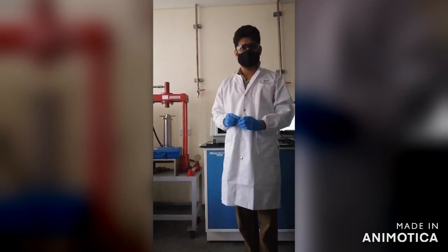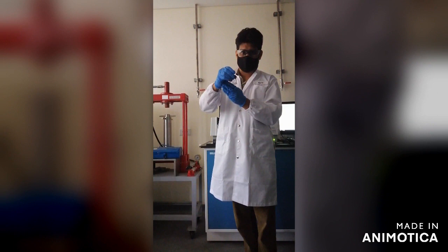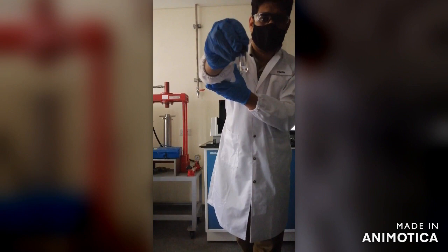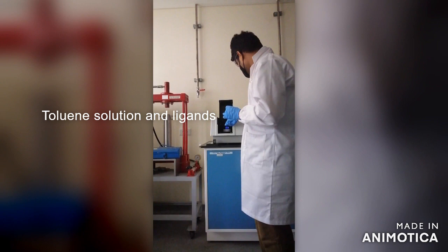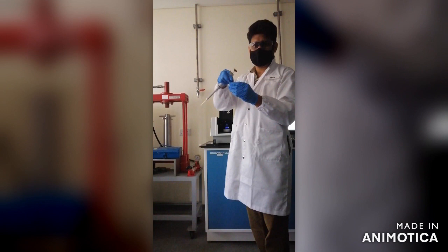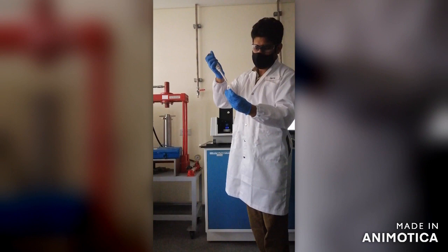Get started, guys. So here I am holding the precursor solution, which is perovskite salts dissolved in a polar DMF solvent. Now I am going to add some of the precursor solution into a non-polar solvent, toluene, in the presence of some ligands. This toluene solution here is placed under UV illumination for clear visualization of the synthesis of these nanoparticles. As soon as we inject this, we'll see what happens next.